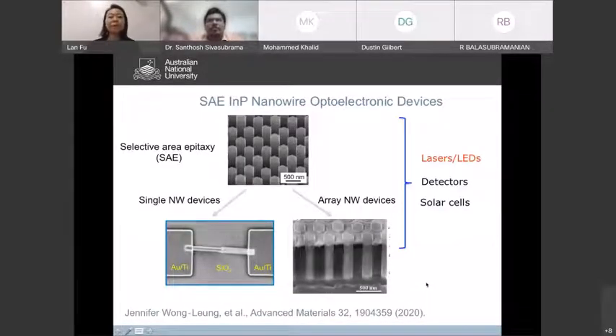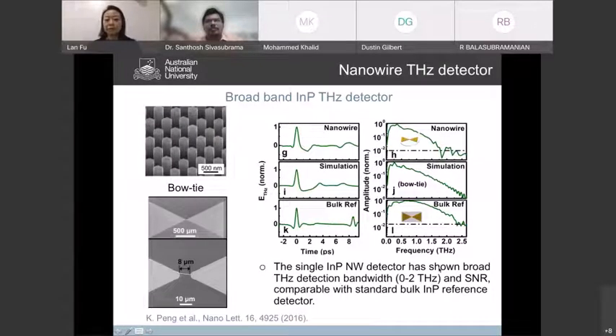So based on this selective area grown indium phosphide nanowire, we're trying to make them into different nanowire devices, either a single nanowire device by making contacts on either side of the nanowire, or we can planarize them and make contacts on the top and bottom of the structure, to make an array nanowire device. So I'll just give you a very quick glance of the devices we made from those indium phosphide nanowires.